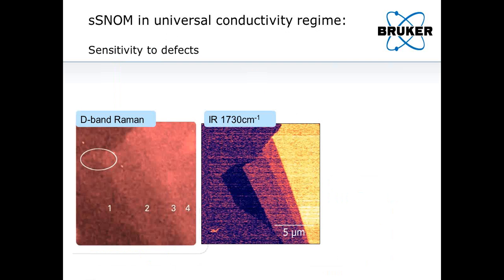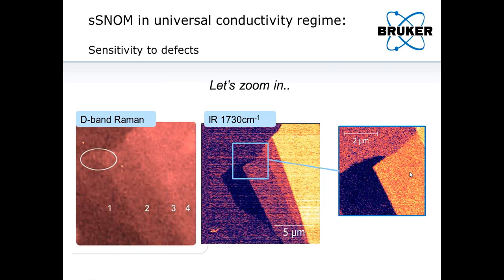So we can also use this image to characterize the defects in graphene. If we look at the D-band Raman image that I showed previously, and we zoom in on that region, we can see some hints of a very similar type of defect in the IR image.